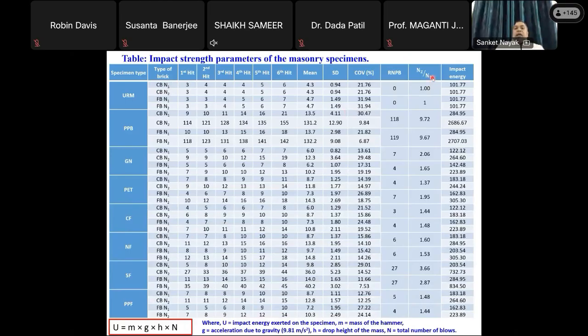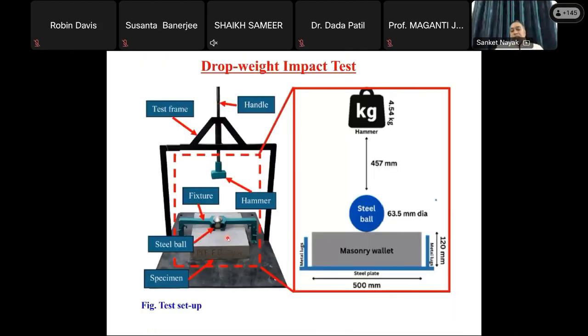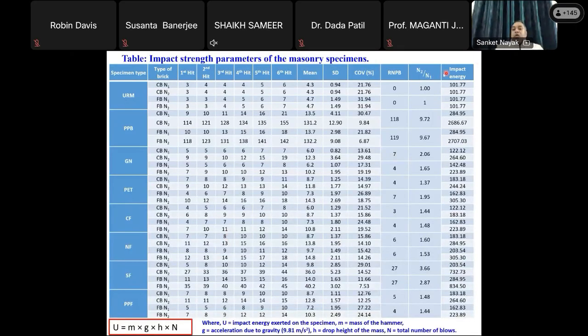N1 and N2: N1 is when the first crack appears after a hit. It does not mean that the first crack appears with the first hit. The first crack may appear at the second hit, and N2 is the hit where the failure occurs. Here the impact energy is calculated using a simple formula, mgh into n. U is the impact energy exerted on the specimen, m is the mass of the hammer which is constant, g is the acceleration due to gravity, h is the drop height, and n is the total number of blows. With respect to that, different impact energy has been calculated for different specimens. Here also we have seen that both the techniques, the PP band and the steel fiber, have performed very well.